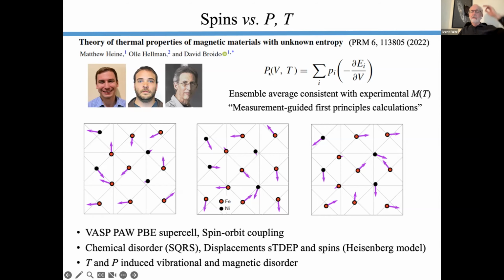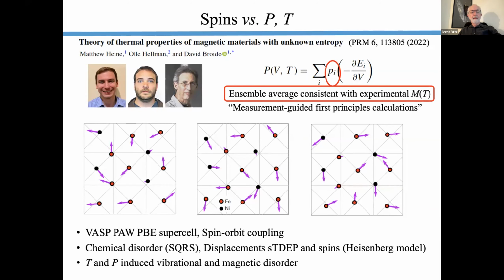And what they really get is a pressure as a function of volume and temperature. That's how the energy changes with volume. And then you have to weight that by the number of elements in the ensemble, which have this piece of I. That's the key thing. And they don't calculate really all of that. They get the magnetization as a function of temperature, and they throw away the elements in the ensemble that are too far away from the experimental magnetization. Otherwise, their computations are pretty impressive. These are plane wave pseudopotential codes with spin orbit coupling, chemical disorder, displacements that cause changes in the exchange interactions between spins, and the temperature and pressure induced vibrational and magnetic disorder.